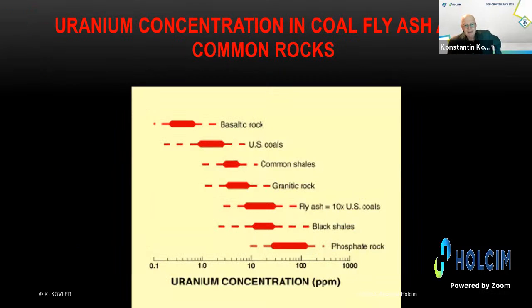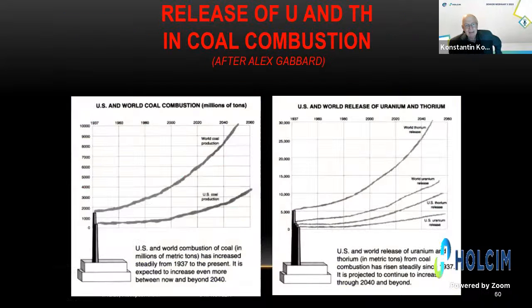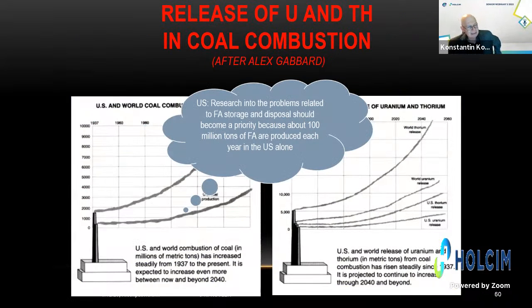Fly ash, for example, starts from the coal. You see, coal is a normal material which has normal uranium concentration. Here is ppm. And then in fly ash, it's data from US coals, it's approximately 1 order of magnitude richer than coal. And then sometimes it exceeds the normative. Many years ago, unfortunately, the chimneys and other combustion installations of thermal power plants were not equipped with good filters.